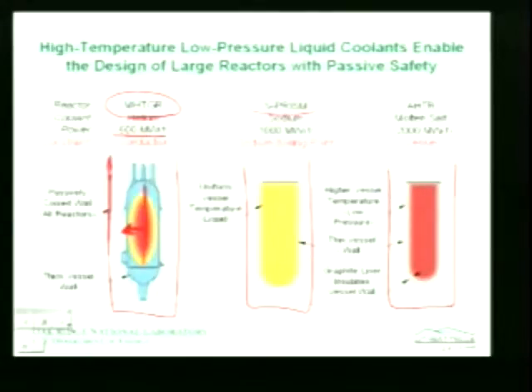Let's take a look at S-Prism. S-Prism is a sodium-cooled reactor. That means the entire vessel is filled with sodium. The temperature difference from the hottest to the coldest point of this vessel in an emergency is about 30 degrees Celsius. So we have very efficient heat transfer from the reactor core to the vessel wall. No 1,000 degrees C, only 30 degrees C. Consequence? We can have a passive decay heat cooling system for a 1,000 megawatt reactor. Remember, all these reactor vessels are the same size.